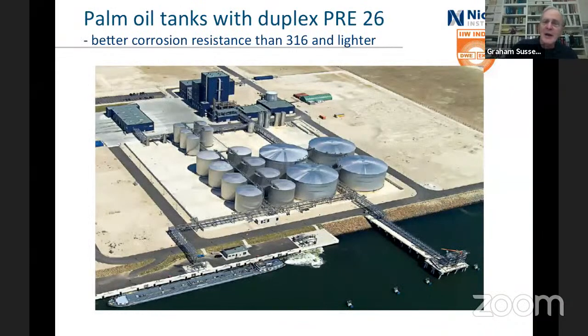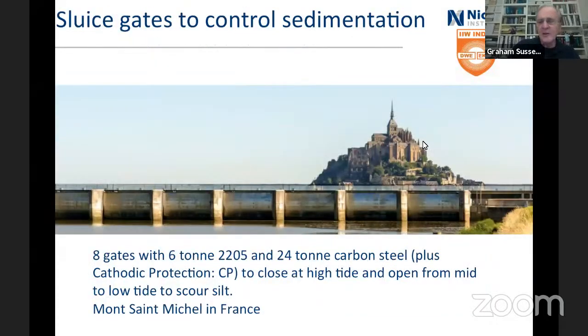PRE. There are alloys with a lot lower PRE, because the PRE for the super duplex is up around 40. 26, better corrosion resistant than 316, and it's lighter because it's stronger. Lots of palm oil. I like this place. I've been and visited it back before they had this. But there's gates, 6 ton of 2205, 24 ton of carbon steel, plus obviously some cathodic protection, to close the gates at high tide, open them from mid tide and scour out the silt. Because it was getting so people could just walk there all the time. Really wouldn't do. The monks didn't like that at all.